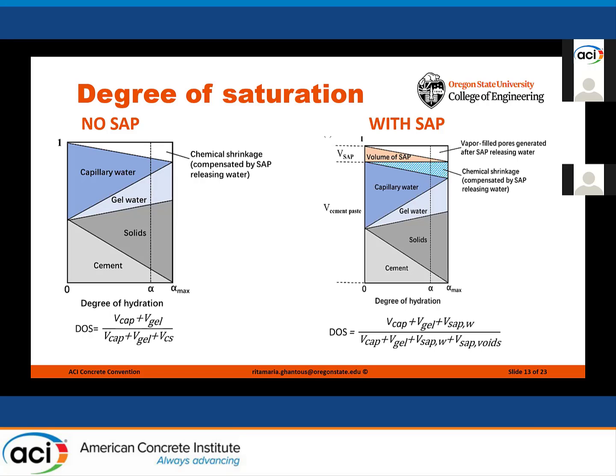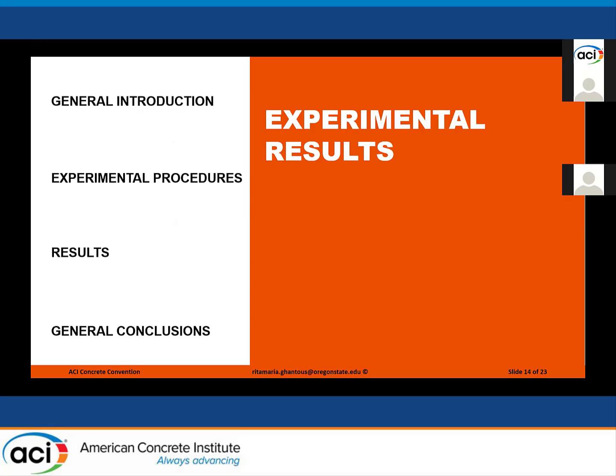The equation we used. So for samples with SAP in them, we accounted for the volume of water released by SAP and then the volume of voids that were generated after the water was released. So for both values, VSAPW, which is the volume of water released by SAP, and VSAP voids, which is the void generated after SAP releases the water, they are both there to compensate the chemical shrinkage. So they are equivalent to the volume of chemical shrinkage. Now let's look at the results we have.